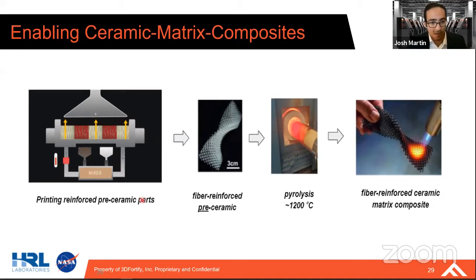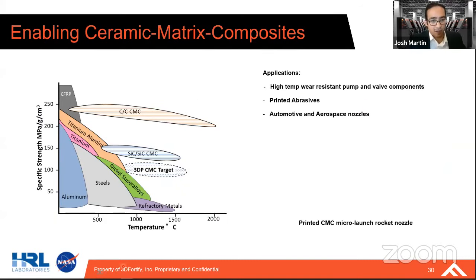And so CMCs are generally the highest performing class of material, which is why they're traditionally very expensive and leveraged primarily for the aerospace sector. And with this, we're able to not only introduce another level of complexity with part design, but also democratize this for a lot of applications that would otherwise have been prohibited from using these due to the cost of these materials. The target of this work is really hitting a class of material that can perform above even nickel superalloys in terms of temperature and mechanical properties. In other words, you can use these parts to print a crucible and melt some steels and aluminum, for example.